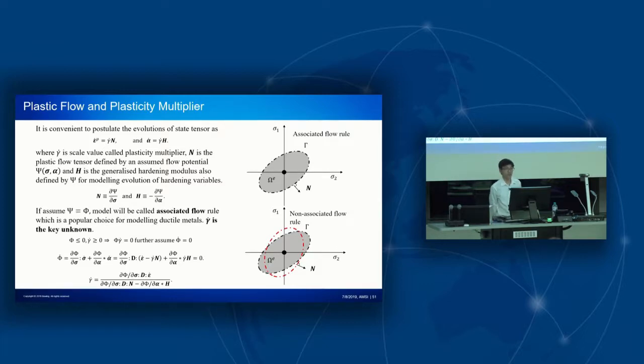Now we have defined the threshold of the plastic deformation, but we also need to know the evolution of the plastic strains. In order to do that, we have to introduce some flow rules for plastic deformation. And for doing that, people assume another scalar function called a potential function. So then using the derivative of the potential function with respect to the strain, then we assume the direction of the plastic strain. Oh, sorry, it's the potential function with respect to the stress.